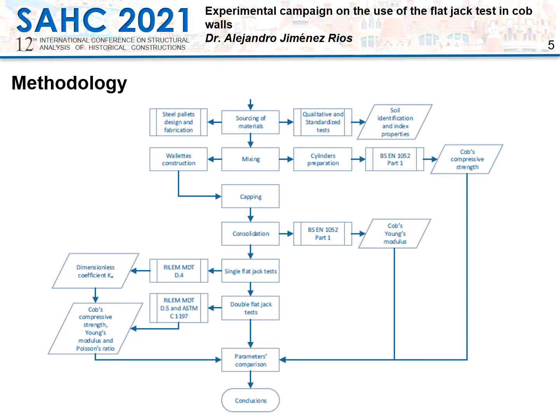The soil used was tested both qualitatively and quantitatively, and its index properties were determined. The mixing of all constituent materials, namely soil, water, and straw, was done manually following the Irish tradition, and with the mix, the wallettes and 6 cylinders were prepared. The cylinders were tested under simple compression to estimate the compressive strength of cob.